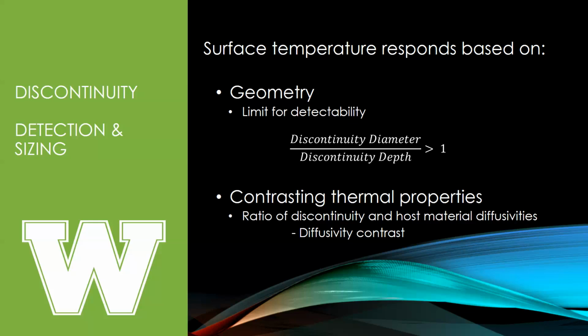But what the effect is, the higher resolution your camera, the more expensive your camera, the larger the area you can image at one time and be able to detect a flaw. But the shape of the flaw is going to play a role in this as well. So there's what's called the limit of detectability. And that is if we take a diameter of a discontinuity and we divide it by the depth, we want it to be greater than 1.